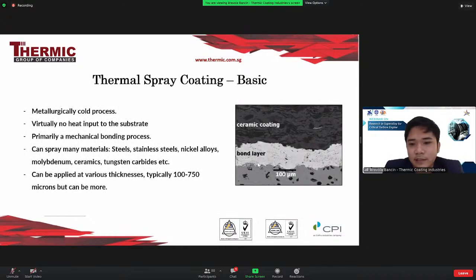That's the principle of thermal spraying. This is the microstructure examples of the thermal spraying process. There is virtually no heat input to the substrate, and it is a mechanical bonding process, just mechanical, not metallurgical like welding. We can spray many materials, and the thickness is typically 100 to 750 microns, but can be more.